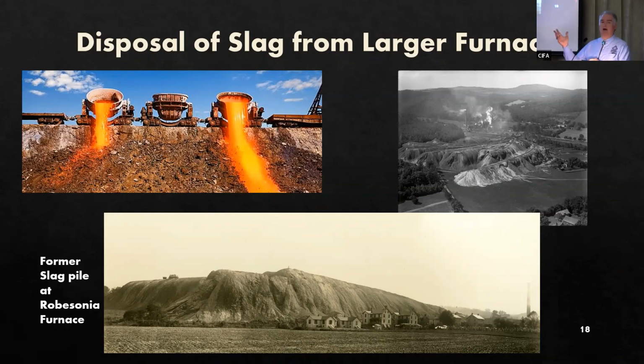You could see smoke coming out of the stack, and you can also see them dumping slag along short rail spurs that proceeded out of the furnace building. Those rail spurs were elevated, so when they dumped, that slag would flow away from the rail spur and create these large slag mounds. In the bottom picture, you can see in the foreground 2- and 3-story houses that are dwarfed by the size of those slag mounds. So that gives you a good understanding of the amount of slag generated and how these later furnaces took care of that slag. And of course, the ore for the Robesonia furnace came from Cornwall.